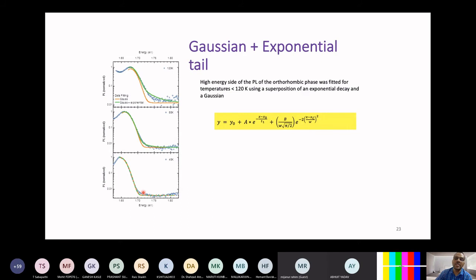So as the temperature increases, the defect states increase in halide perovskites because the molecular rotation and vibrations are increasing in the octahedra, and that gives rise to more defects. And hence, in order to fit the PL of high temperature data, you need Gaussian plus exponential. But the moment you quench all those phonon assisted absorption and emission phenomena, then you can fit your data with a single Gaussian. So that was a very nice way of showing the data. This paper is highly cited, and I will say semiconductor physics students should indeed read this paper.